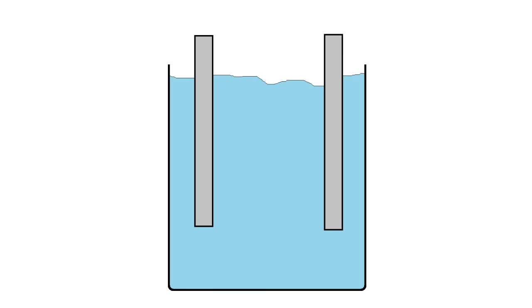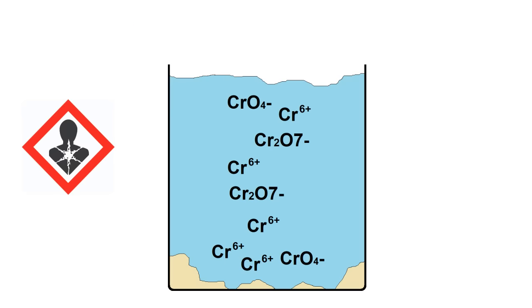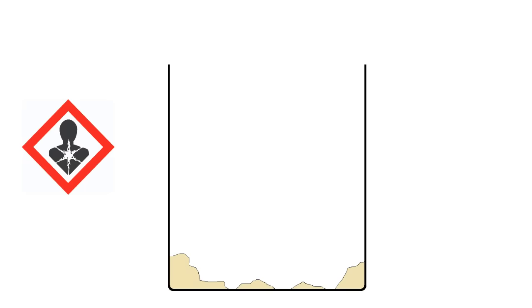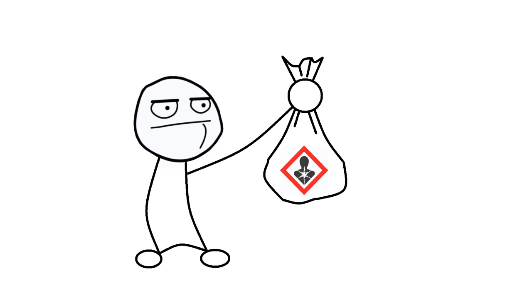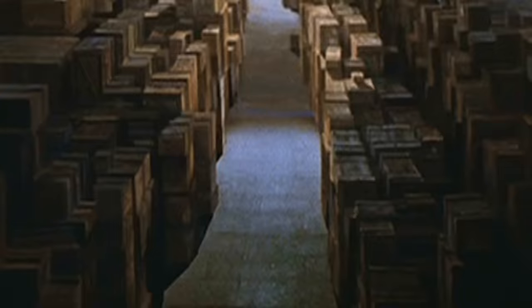Anyway, there's one more thing I need to mention about electrolysis. If you're using stainless steel electrodes, they'll last for a reasonably long time, but not forever. Over time, they'll release various chromate salts into the water, which are bad for your health. Some of these could even have hexavalent chromium, which is particularly nasty. So if you have to get rid of your electrolyte after hundreds of hours of use, don't dump it down the drain. Put it in a bucket, let the water evaporate, then collect the precipitate in a plastic bag, and drop it off to a toxic waste disposal site, or stash it away in a government warehouse.